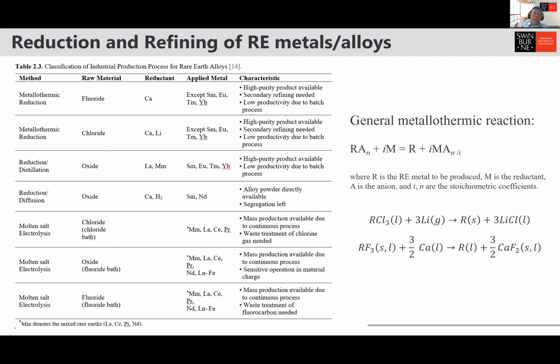So once we get those rare earth elements, usually in terms of chlorides, fluoride, and oxide, we can then further process to make them into alloys. There are different types of process that we can choose. We can take metallothermic reduction, for example. Usually we use that one for fluoride and chloride. The reaction on the right shows the general metallothermic reaction.